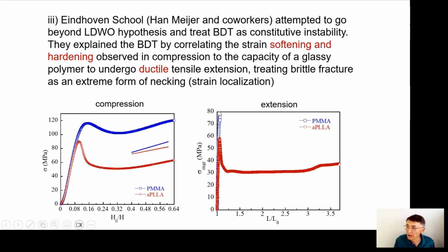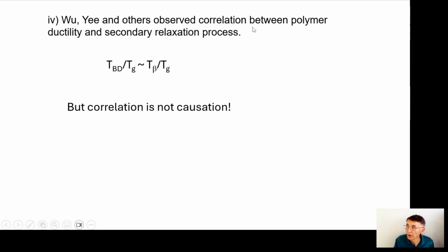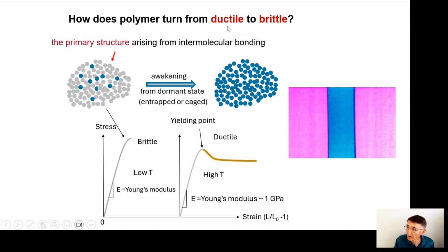So then there is this continuum approach of Eindhoven's group, which was really treating brittle failure as an extreme form of strain localization, and they tried to do it at the continuum level, mathematically showing that the features of strain hardening and softening could influence the outcome or the degree of strain localization. Again, it's a continuum level. It doesn't go into the details of what happened to the molecules. And there's a more molecular approach that tries to correlate secondary relaxation with the brittle-ductile transition, but this correlation is not causality.